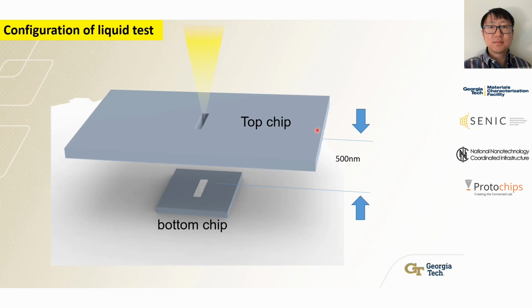The liquid test we perform is in the liquid cell holder, as I mentioned, that's produced by Protochip. We have two chips to seal the chamber. Between these two chips, there is about a 500 nanometer spacer. This 500 nanometers can guarantee enough flow of the solution across the chip, and it can guarantee relatively good enough resolution to resolve the sample.